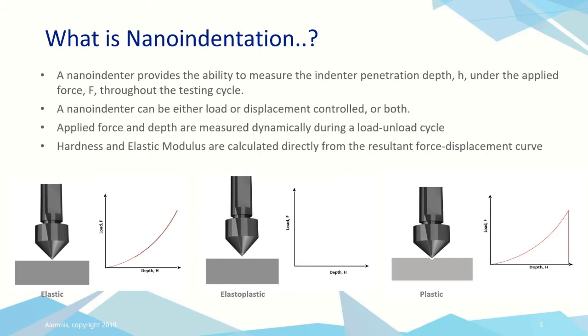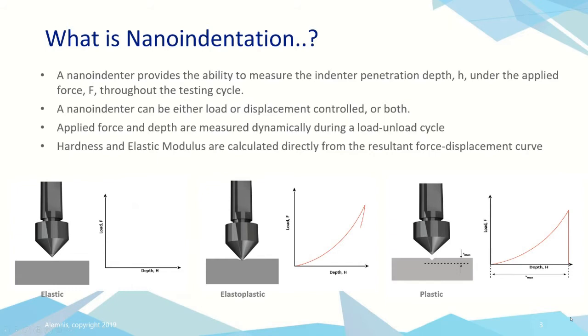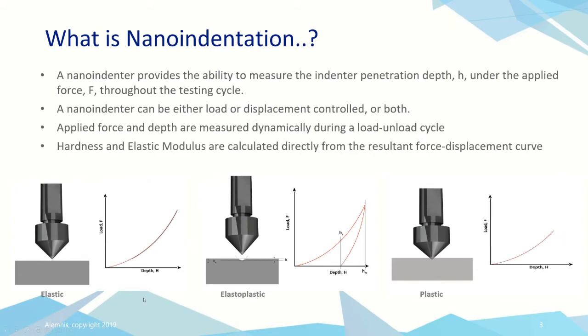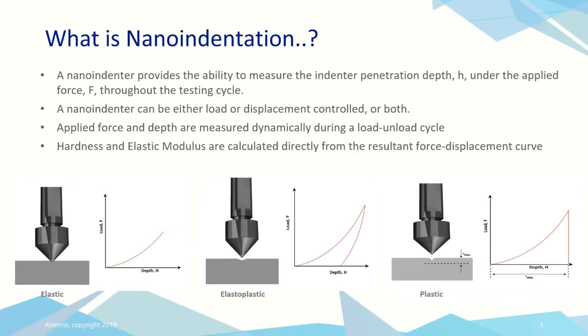So if you look at the 3 examples here, these are for different material categories. On the left, we've got elastic materials, so we can load up to a maximum and then unload, and there's basically no hysteresis between the two curves. This would be like low load indent into glass, for example, which is very elastic, or into a polymer.